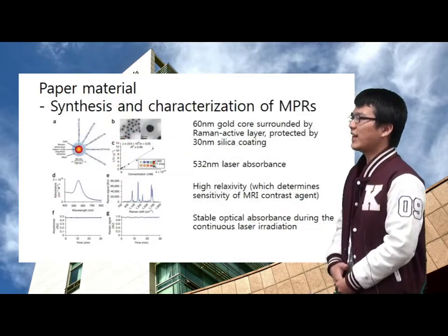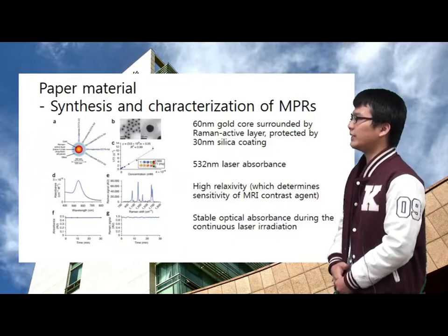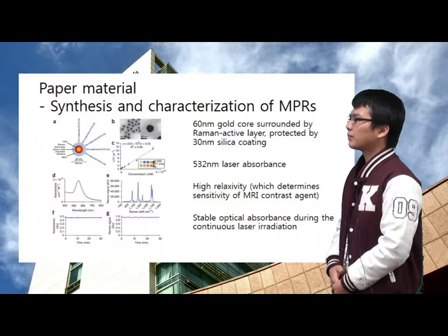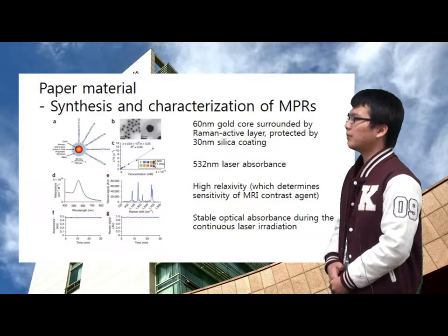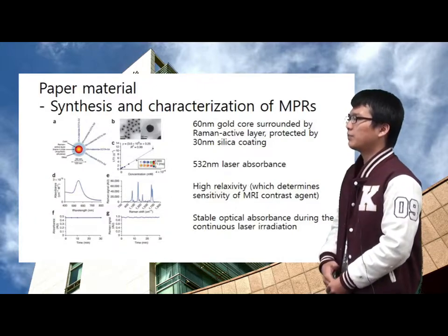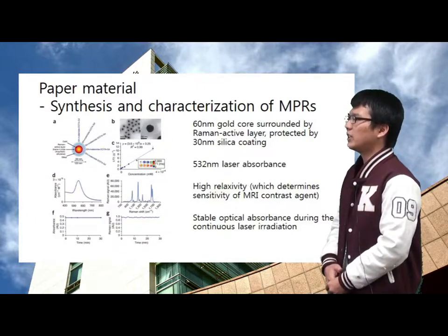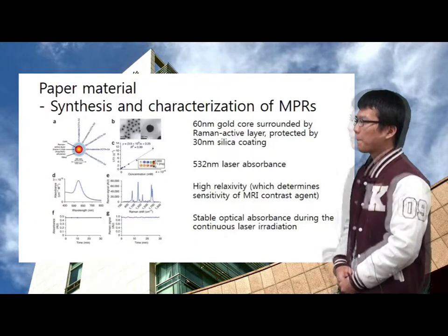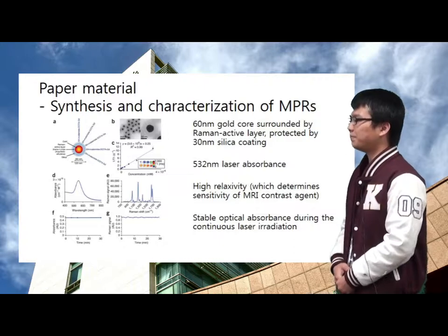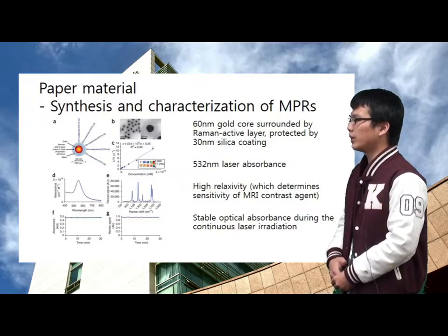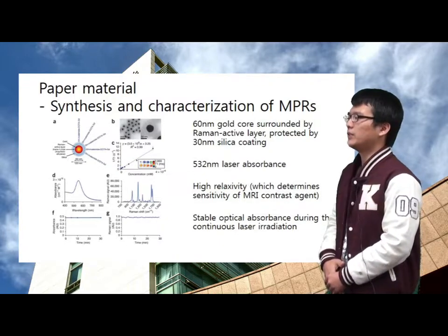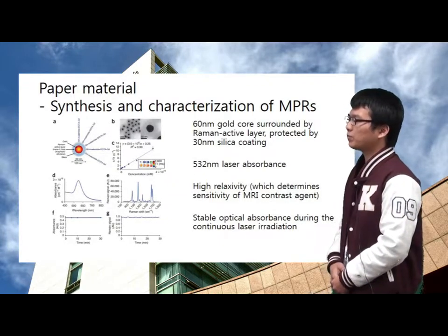First, they synthesize and characterize this MPR nanoparticle from many points of view. This 60 nanometer gold core surrounded by a Raman active layer is protected by a 30 nanometer silica coating. Laser absorbance, relaxivity, and optical absorbance during continuous laser irradiation are confirmed in this figure.